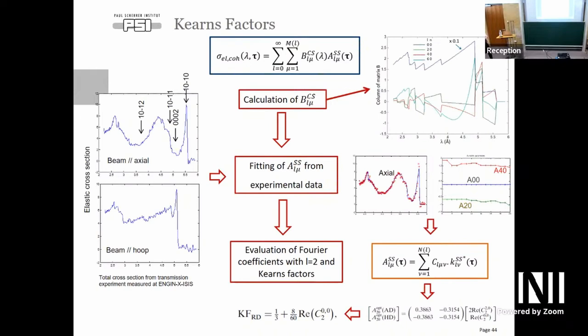Yeah. There's a lot of things that we have to do. I mean, did you have to take a lot of counts to do that? Yeah, that's the point. Again, this is an experimental thing. And we have a lot of noise, which is expected in experimental data. So a really important key aspect of all this analysis is how far you will go in order to cut your different coefficients, because if you start fitting even the noise, you don't want to fit it. Exactly. And that's another thing. Yeah, in this material, even